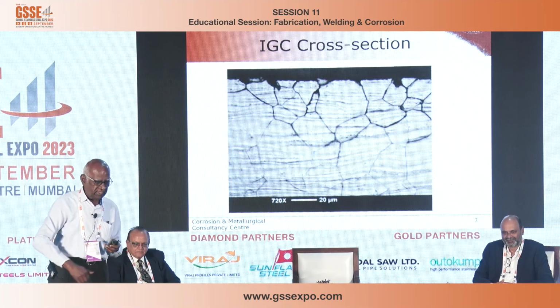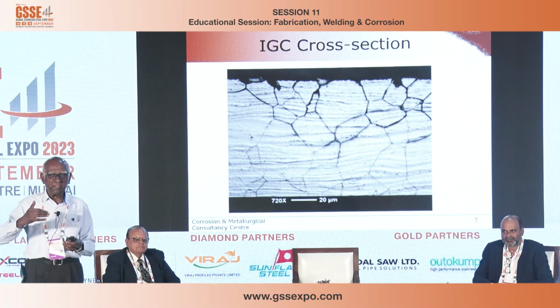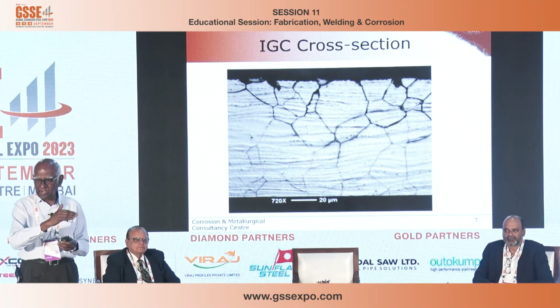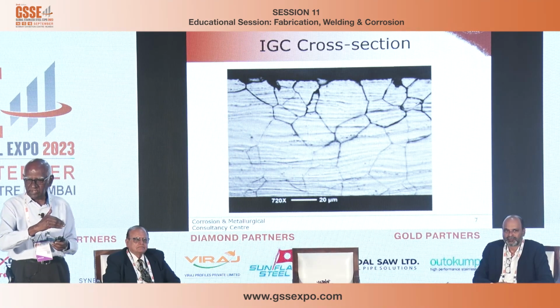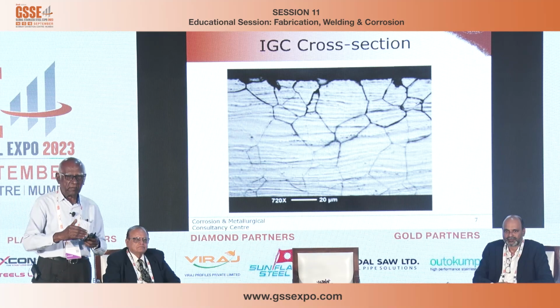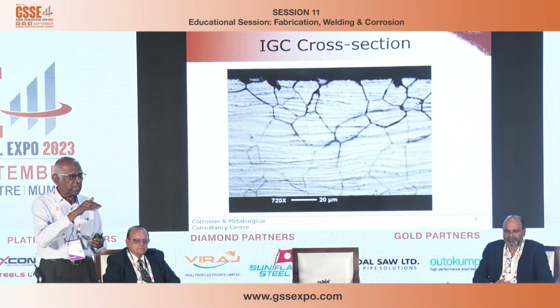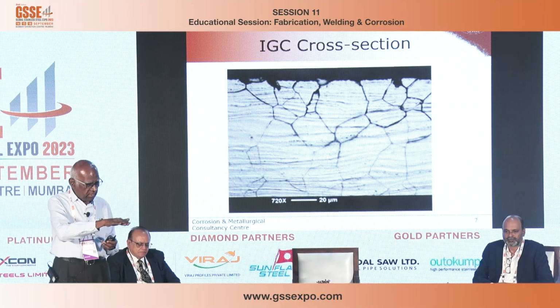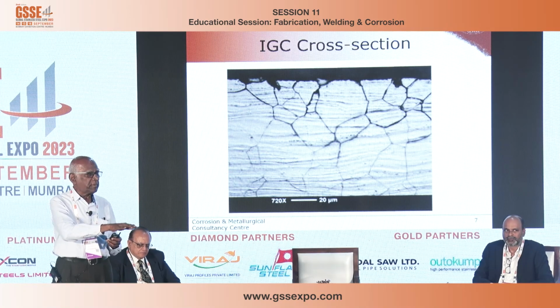So this is how the thickness is lost. You can see part of the thickness is corroded by looking at the dark lines. Those are the dark lines like a mud pattern. Those are the dark lines where corrosion has occurred, whereas on the top surface, you don't see that much corrosion.